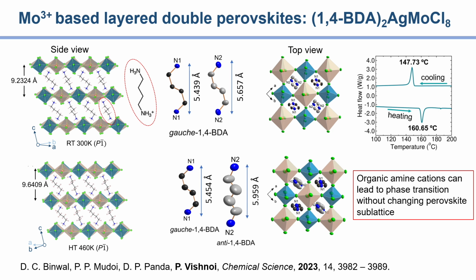And in this molybdenum compound, where we have diaminobutane in the interlayer gap, the lattice is robust and very strong and stable. But essentially here we see at room temperature, we have cations which are in 2 different forms. One, we see there's a difference in the thermal parameters. And then when we heat this compound, one of the butane diammonium cations changes from gauche to the all-anti form. So there's a partial change in the conformation, and this is clear from the cavities that we have here, where the ammonium cation sits. We see selectively one of the cations become large at high temperature, and this leads to a phase transition around 160 degrees C, which is reversible.